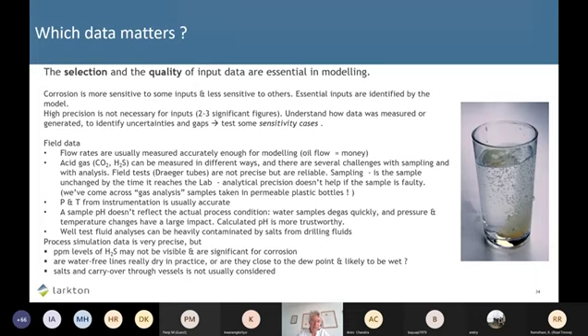Now, process data is often very precise, but the ppm levels they give might not have enough significant figures to see ppms of H2S, and that can be very important. You have to question whether there's water in lines that they say are water-free. And you have to bear in mind that salt carryover is not covered by process engineering, and we often get the issue about when we're selecting, particularly CRAs, do we have a chloride concentration in this water or do we not? Is it salt-free? How much is that carried through in droplets through a plant, for instance?